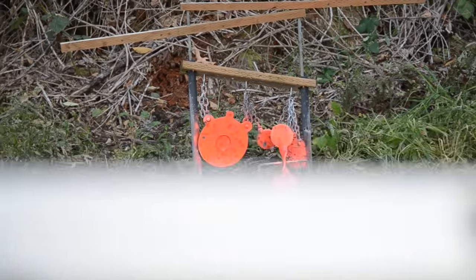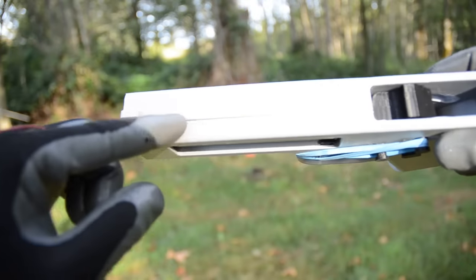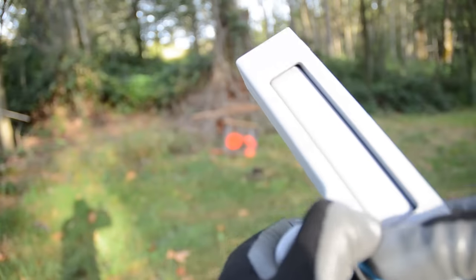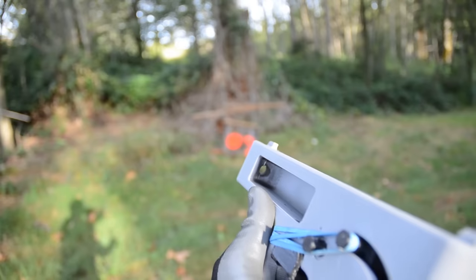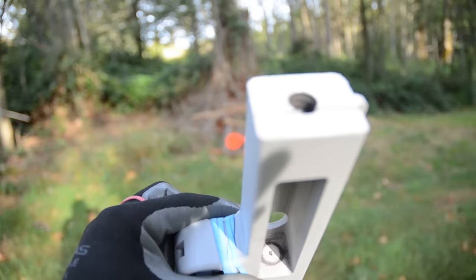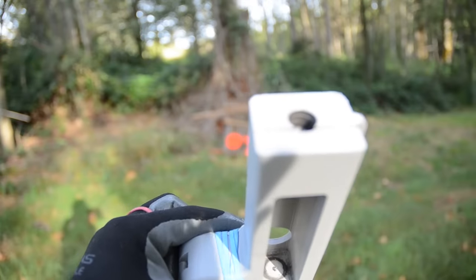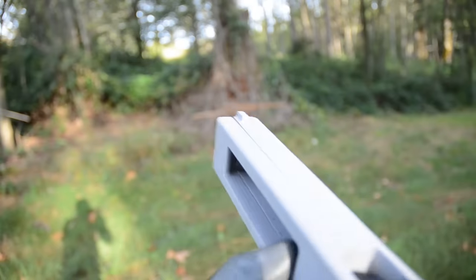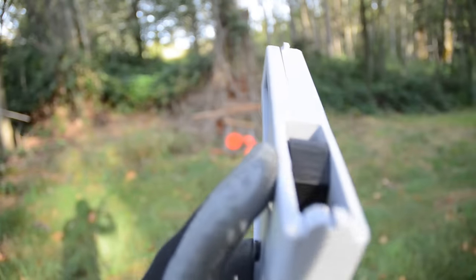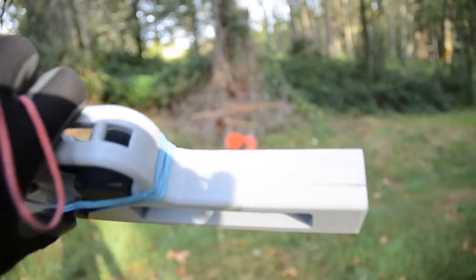Let's see if we can get this to focus — maybe we'll have to go back in the shop. Remember that layer separation I had? It went way further back. I think what's happening is the front of the barrel is curved and so is the recess it sits into, so pushing forward it's acting like a wedge. I could probably fix this — I could ABS glue this all back together — but this would be a nice wall piece. Next time I'll have to watch out for that layer separation; it was really unusual for my printer. You can see the line goes all the way back here — it's like a grain of wood. If you start a crack and keep beating on it, it's going to spread really easily. It goes all the way down the bottom too.